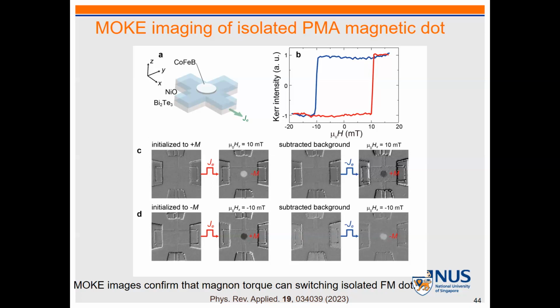We always use our MOKE imaging. So this is now an isolated PMA CoFeB on top of nickel oxide, and we just flow charge current. You can see we can switch from white to black or black to white, and in this case it is PMA. But of course, we have to apply a very small in-plane magnetic field to switch.